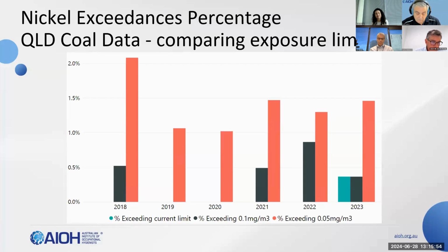By the way, out of that, there were only very few samples that exceeded. I think in 3 years, there were 9 samples altogether that exceeded 0.05 milligrams per cubic metre. So pretty small exceedance rates. We also had some chromium data come through. I don't have a graph for that, but the exceedance rates for chromium were similar to nickel, and these were less than about 2 to 5% of the current limit of 0.5 milligrams per cubic metre.